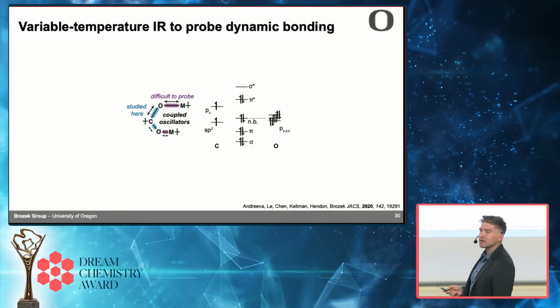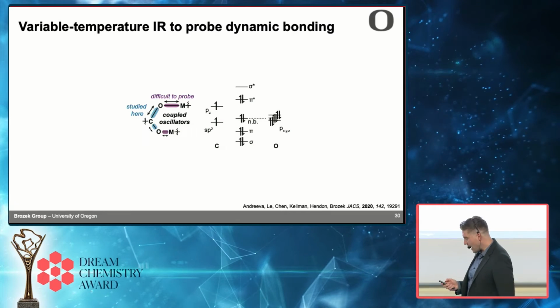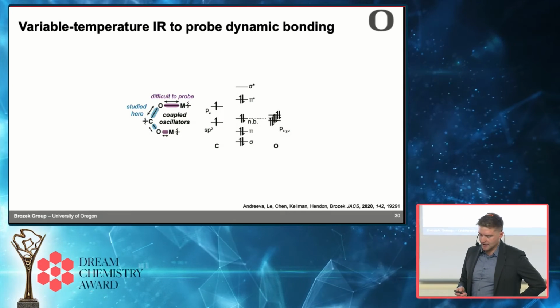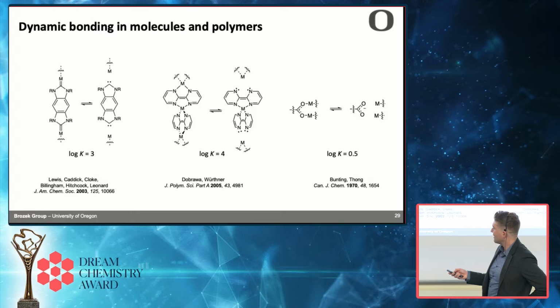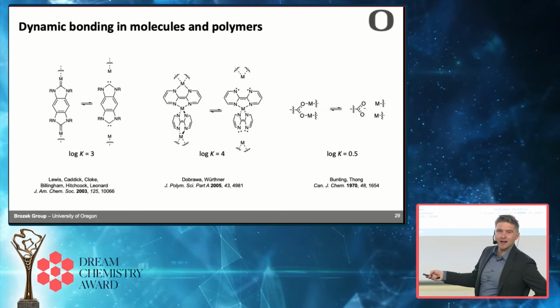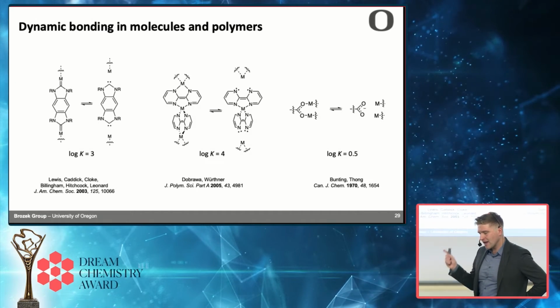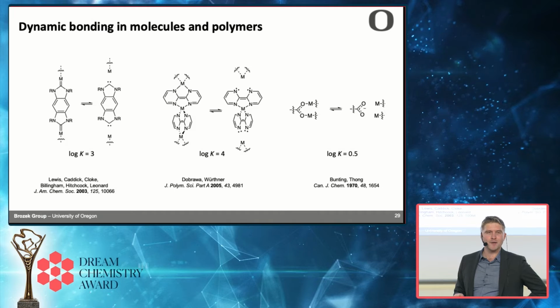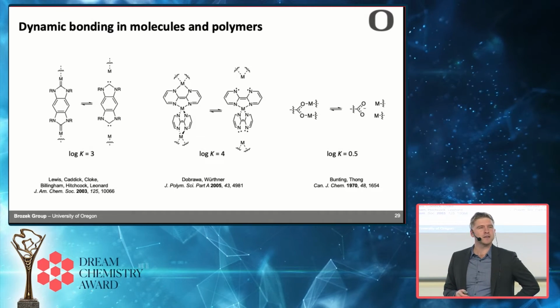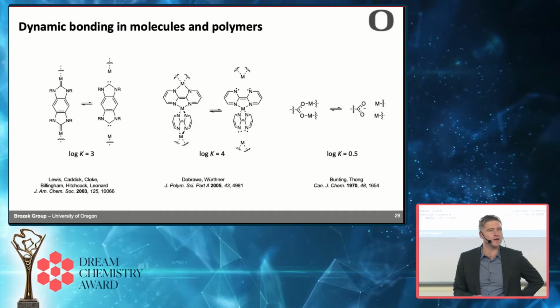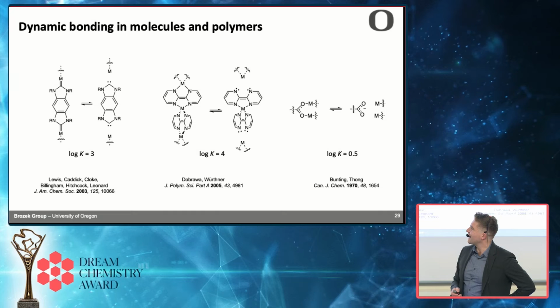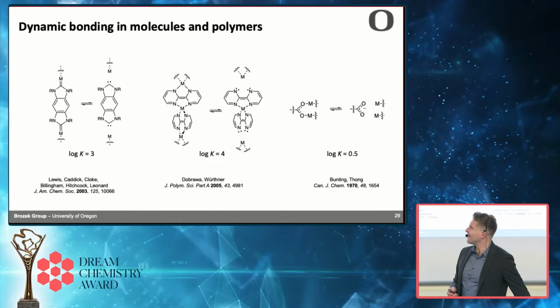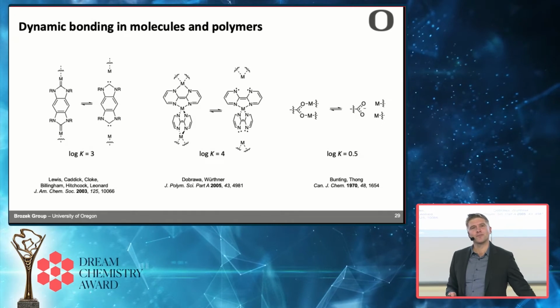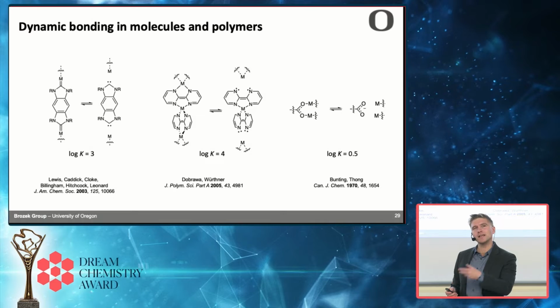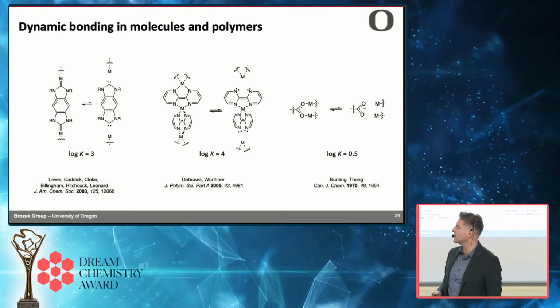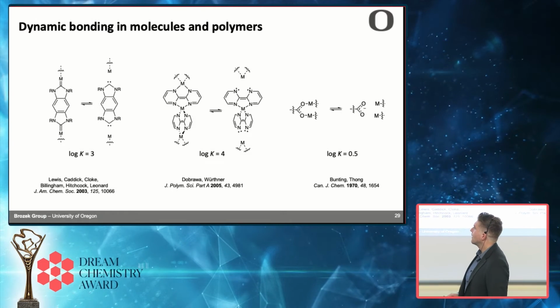So I want to be able to measure that for a MOF. And we had this vague idea that, in fact, it was inspired by the way that they measure the equilibrium constants for this material. I figured, if the bonding in a MOF is dynamic, I should be able to use some kind of vibrational spectroscopy to see that. And I had this intuition that as you heat up a MOF, the vibrations, if they're really getting weaker, they should redshift. That was my intuition.